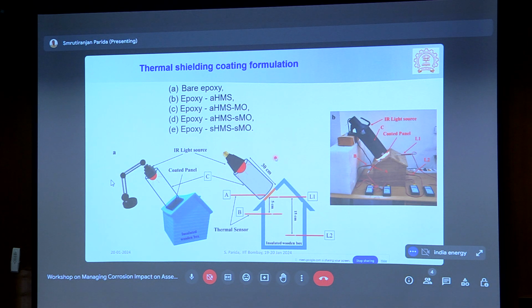So basically, to develop into that state, we have tried many optimizations. We made a comparison study of the bare epoxy with the activated hollow microspheres. Also, we added activated hollow microsphere with unmodified metal oxide, then activated hollow microsphere with the modified metal oxide. And we created all these coatings, and this is a kind of homemade setup we created. So this is a an IR lamp, and we irradiated a panel which is coated with about 65 micron of the epoxy coating containing a certain weight percent and ratio of this mixture.